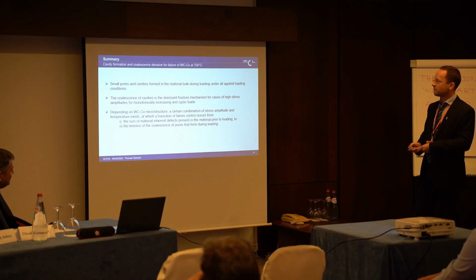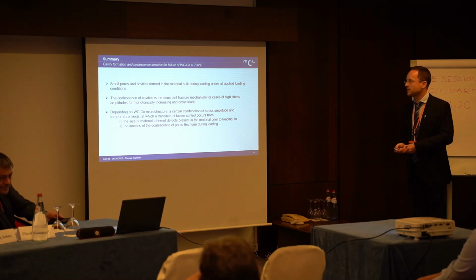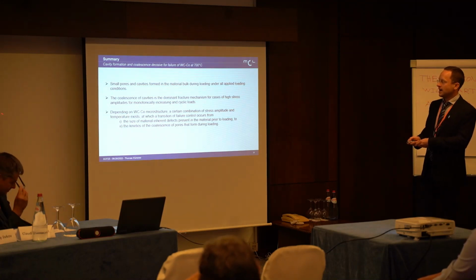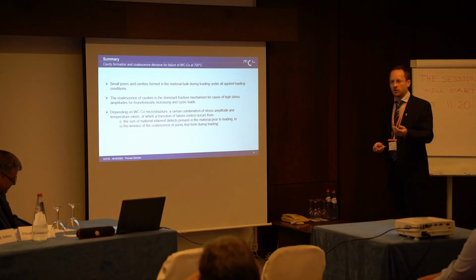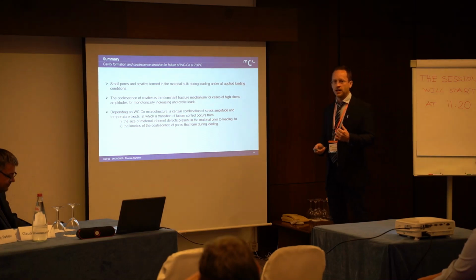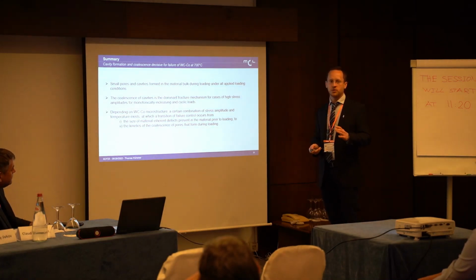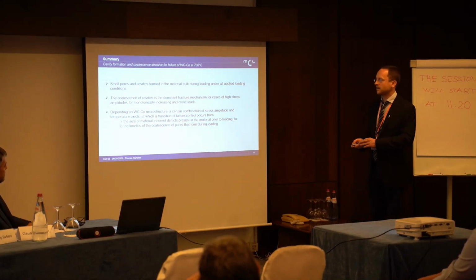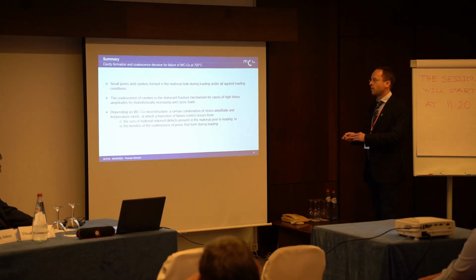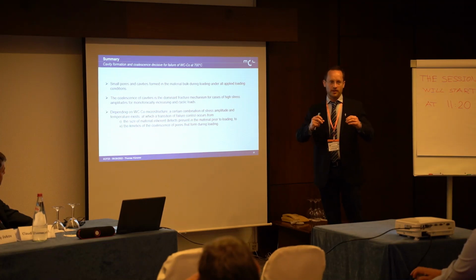And this is something that is interesting in my eyes because the size of the interior defects plays a role for large effectively loaded volumes and low temperatures, and that's a lot of applications of this material class, hard metals. But the kinetics of the coalescence, supported by plastification, are important for small effectively loaded volumes.